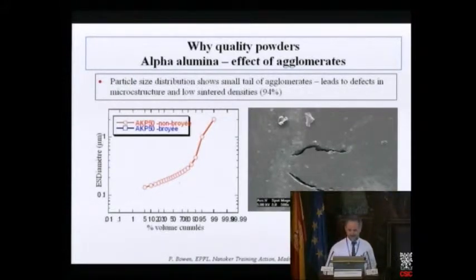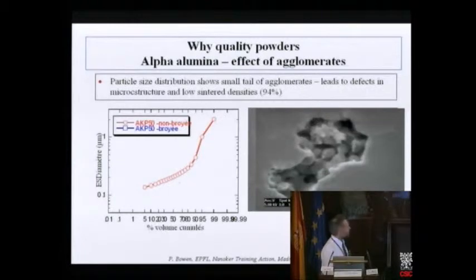And this is a high quality powder. You see also on a smaller scale, a couple of microns now, these defects. So these are hard agglomerates, which when sintering already have pore size which is too big, and they don't disappear. If we attrition mill, just for a short period of time, 30 minutes, 1 hour, you can see that you can change this tail, you can get rid of the agglomerates, and we have something which follows a log normal distribution, right up to 99% of the particles. So we can get rid of this tail.